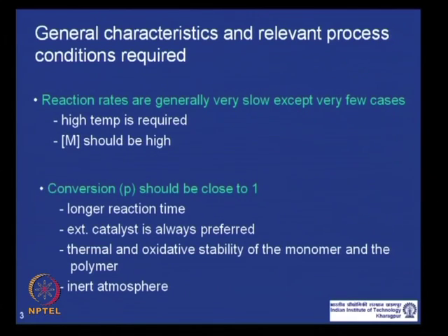And we also know that at high temperature, if there is a presence of oxygen, then thermo-oxidative degradation is a very feasible way of degrading any organic molecules. So, it is always preferred that the reaction, if possible, should be done in an inert atmosphere like a nitrogen or argon atmosphere, so that you are taking away, or minimizing, the possibility of thermo-oxidative degradation of the monomer or the resulting oligomer or polymer molecules.